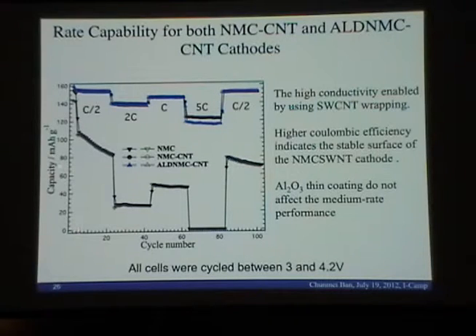This shows the capacity versus the cycle number, and we're testing at different rates. C means discharge or charge in 1 hour. C/2 means we use 2 hours to charge or discharge. And 5C means we use about 12 minutes to discharge or charge. And then we find that this black one is the primary, just the pure bare material in the electrode testing.